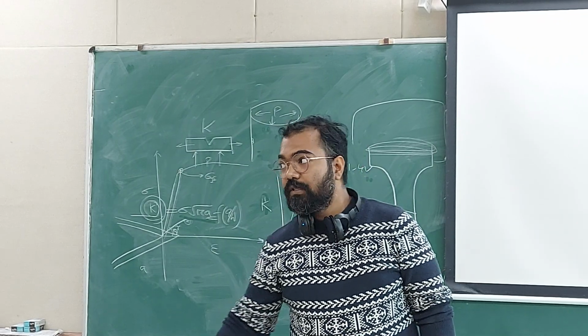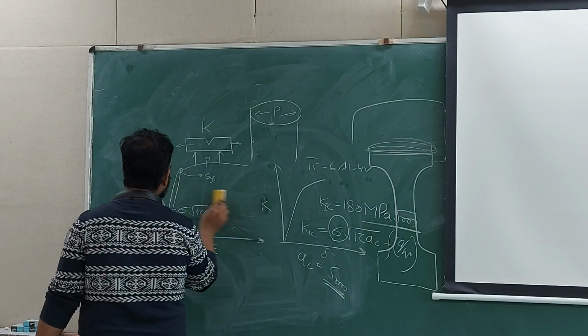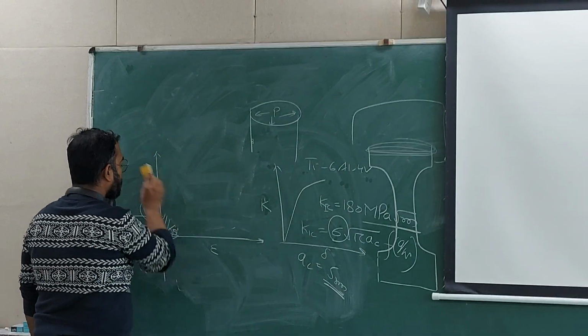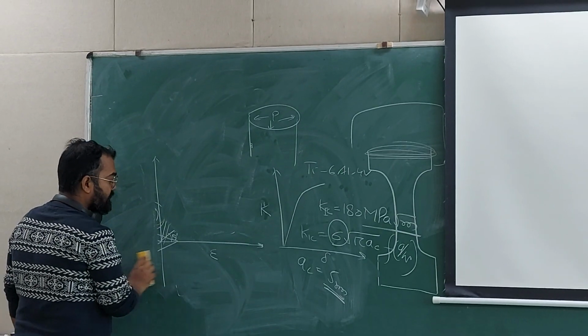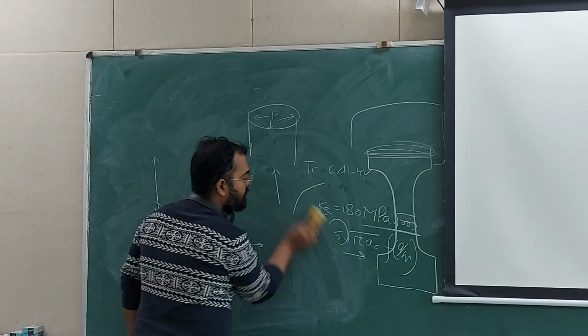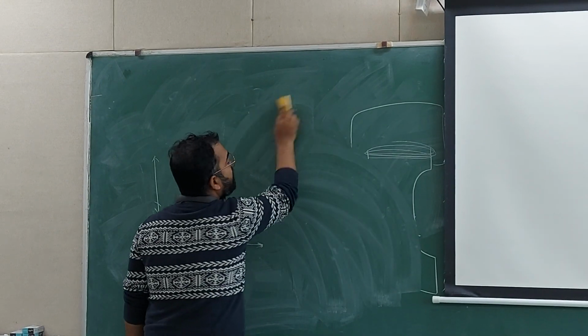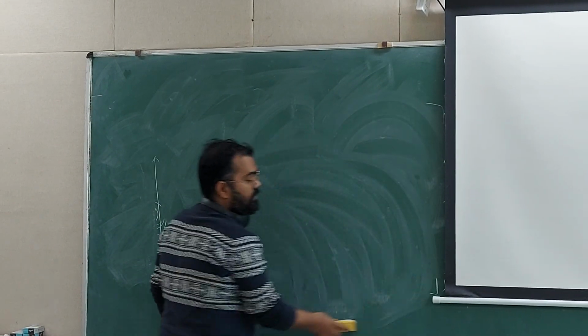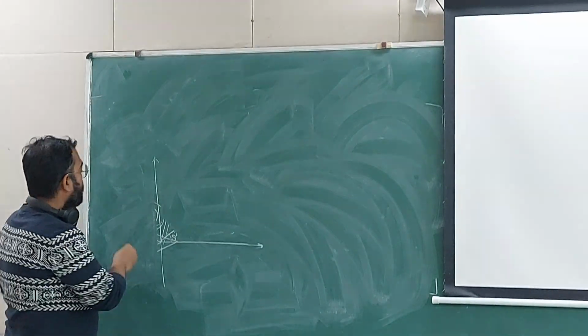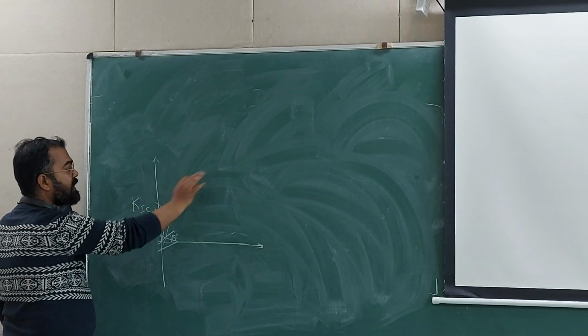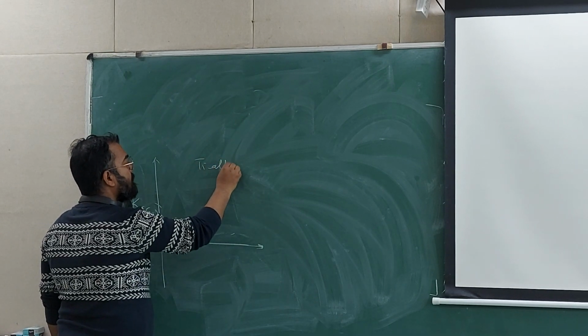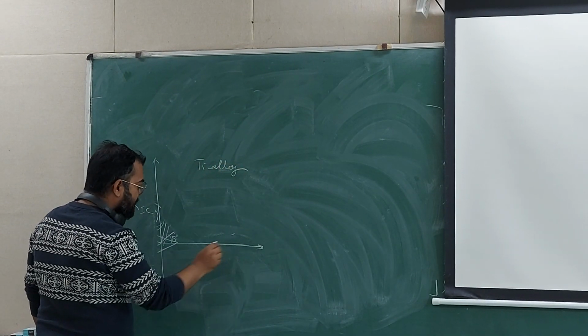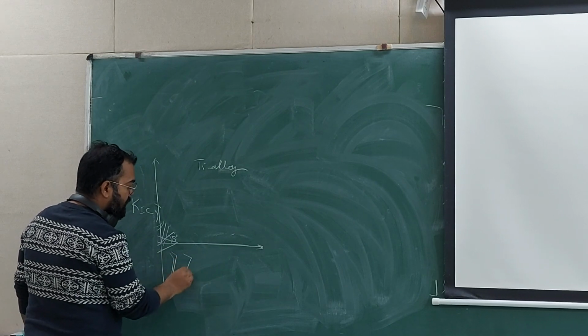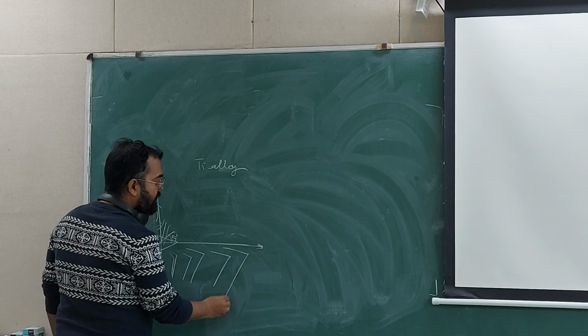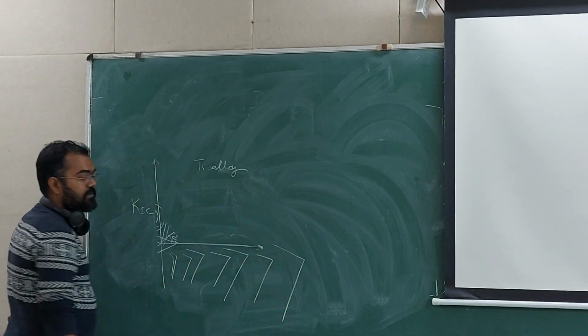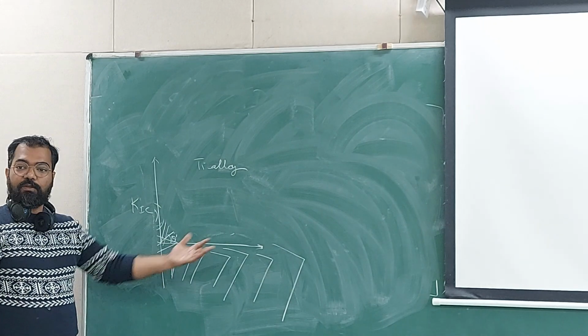So this K1c appears to be a material property, at least a design criterion for sure. But there is a size effect. Before we go into that, since we are talking about it, I'll finish it. Calculate K1c for the same alloy, let us take a titanium alloy, and I do the testing for a very thin sample, and I keep on increasing the thickness, from a very thin sample to a very thick sample.